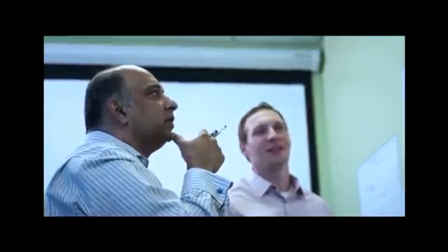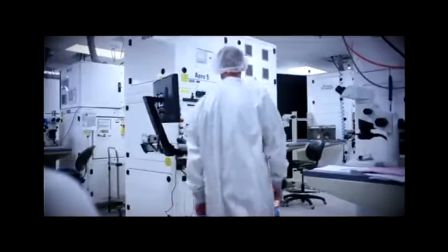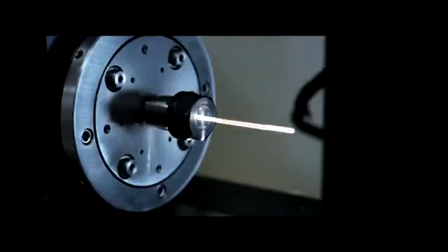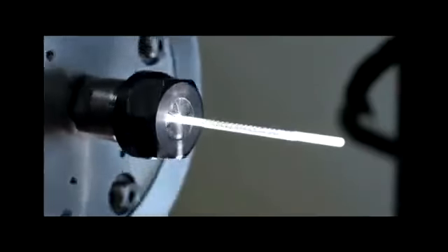To find the design inputs that provided the best outputs, Boston Scientific explored more than 100 stent design iterations, tested numerous geometries and materials. The result is a hybrid architecture stent that delivers on each design and engineering target. Optimized strut dimensions for outward radial force, compression resistance, and durability. A peak to valley pattern that provides flexibility and a smooth lumen on any bend. Closed-end cells for deployment stability, and open middle cells for greater flexibility. A best-in-class peripheral stent, laser cut out of nitinol.